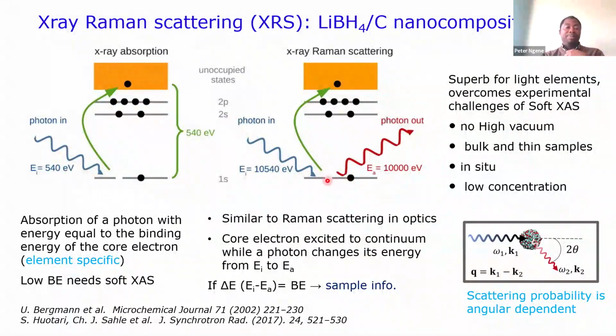you can come with high energy that is much higher than the binding energy of the material you're interested in. And then basically you have your detector that is fixed at a certain energy. And what you really measure is just the difference between the incoming energy and the outgoing energy. And once this difference, which I try to put here, is equal to the binding energy of your sample, then you're going to get a signal. And this also has an angular dependence, which is a bit more complicated, but with this, you can actually get even more of the properties of the material by looking at the angular dependence of your signal.